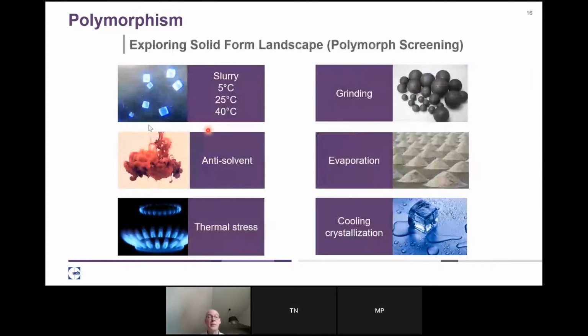And this is in fact why, typically during development, we do a polymorph screening to explore the solid form landscape. So we put crystals in a slurry in different solvents at different temperatures. We precipitate crystals by anti-solvent. We put thermal stress, heat, cool. We grind crystals to see if the mechanical stress creates another type of crystal. We evaporate,